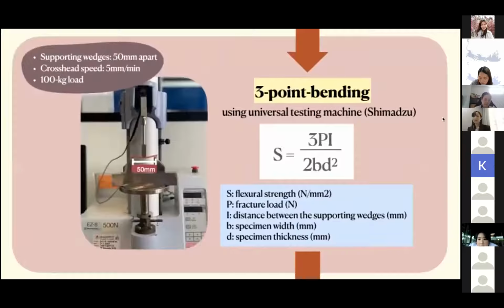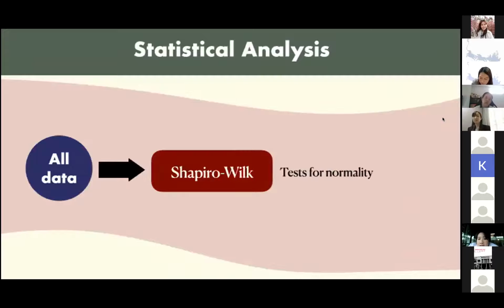The flexural strength of specimens was tested by a 3-point bending test using a universal testing machine, Shimadzu. The specimens were centered on the device. Supporting wedges were 50 mm apart with a crosshead speed of 5 mm per minute and 100 kg load. Specimens were loaded until fractures occurred. Flexural strength was calculated by the manufacturer's software using the shown formula. After data collection, the Shapiro-Wilk test was used for normality tests. The results show normal distribution, so parametric statistical tests were proceeded.